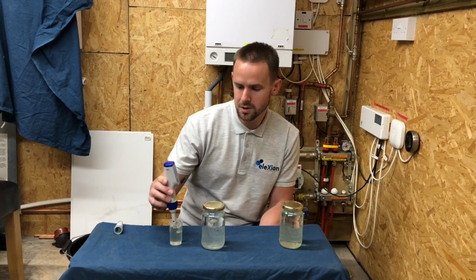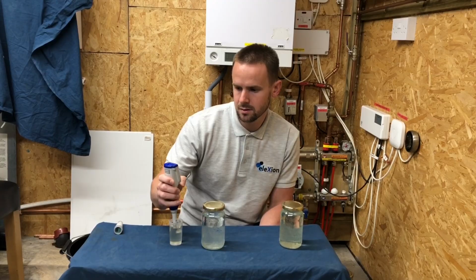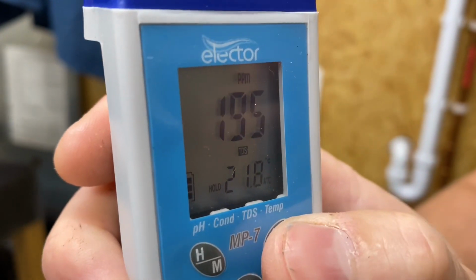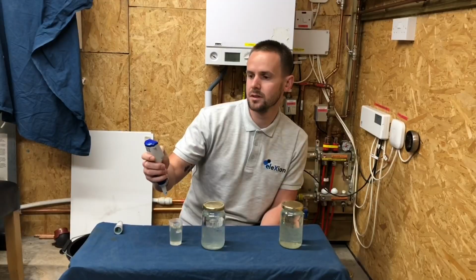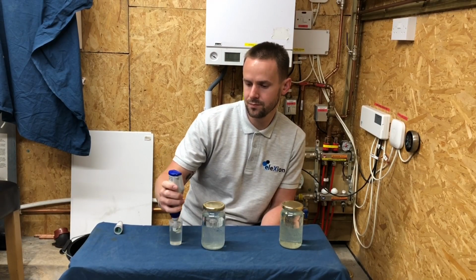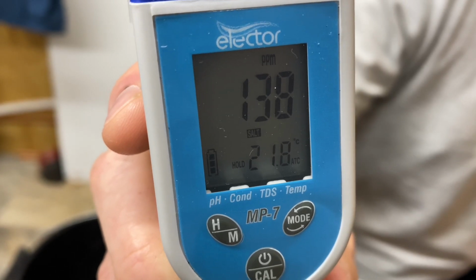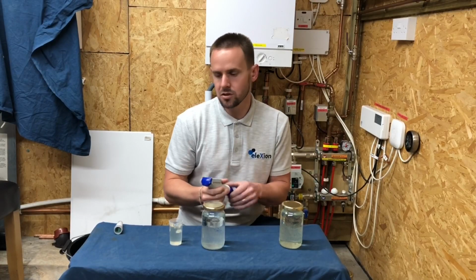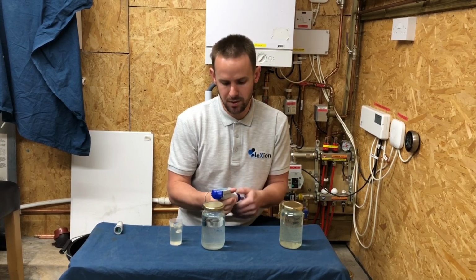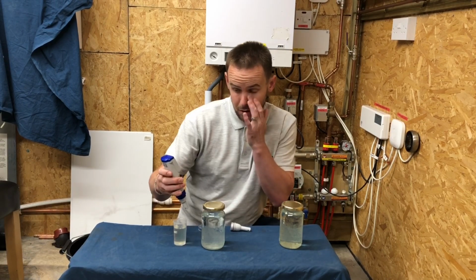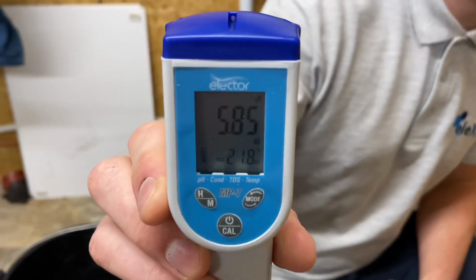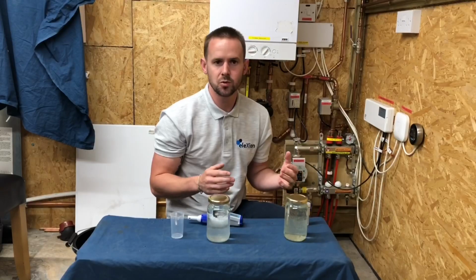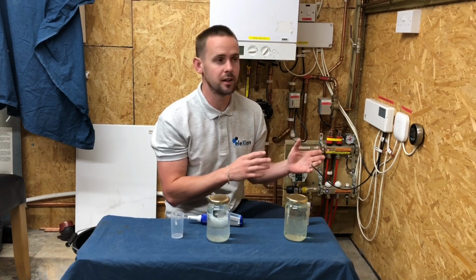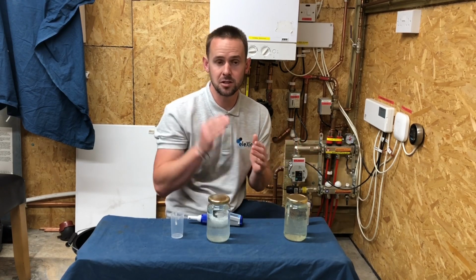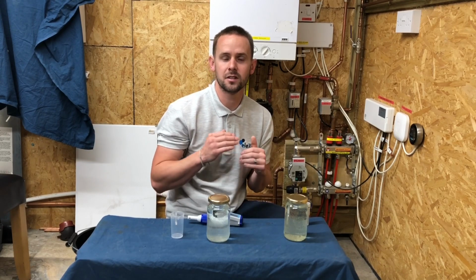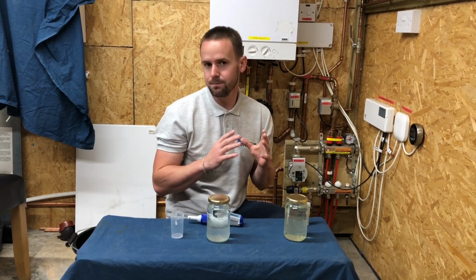Just going to check what the TDS is. The TDS is 195, and then I'm just going to check what the salts are. 138 parts per million. Now we're going to change the probes and check the pH. We've got a very low pH here of 5.85. From those test results, we can see that there clearly was some residue cleaner left in the system. Our pH had decreased and our conductivity had increased. So basically that's not what we want.